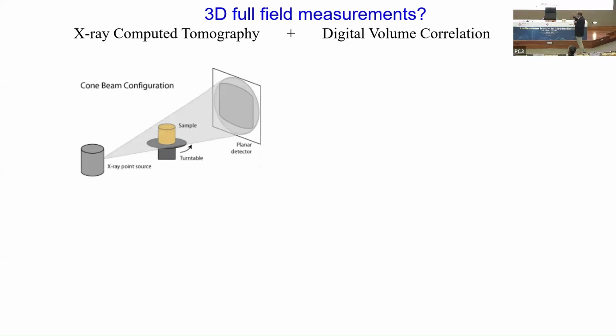So if you want to do full 3D measurements with X-ray, which is essentially going to be using X-ray computed tomography and digital volume correlation together. So the idea is, of course, you have X-ray tomography where you keep rotating the specimen, get these projections, and then you do a reconstruction of the volume.